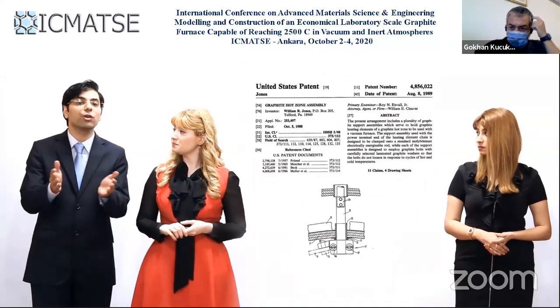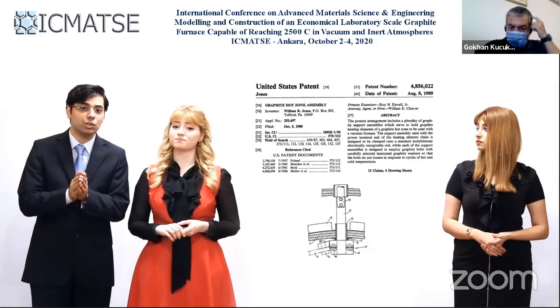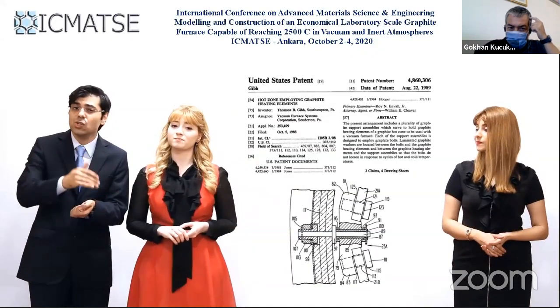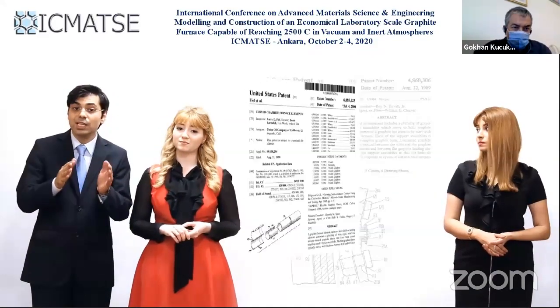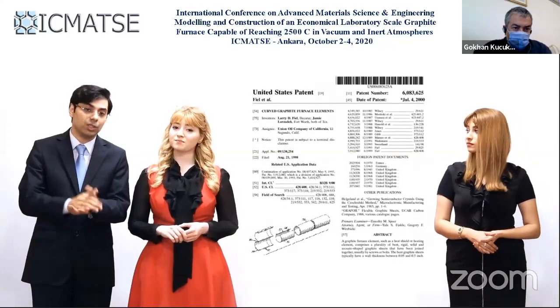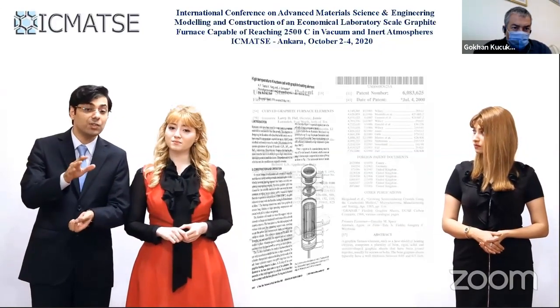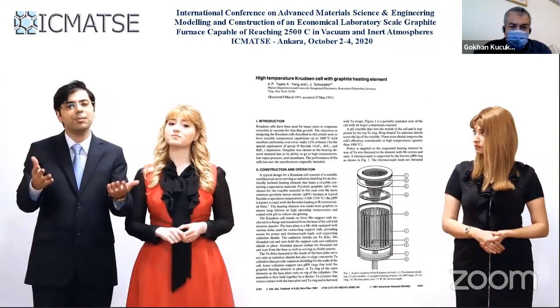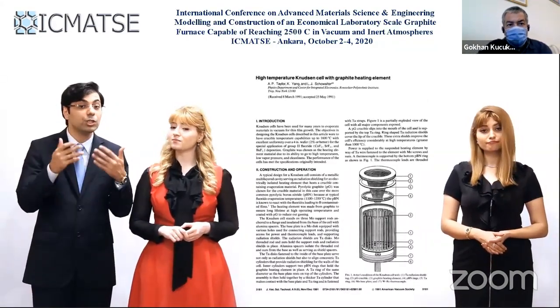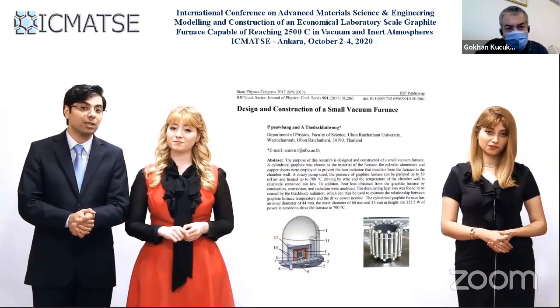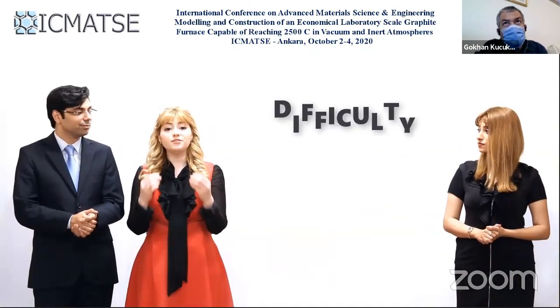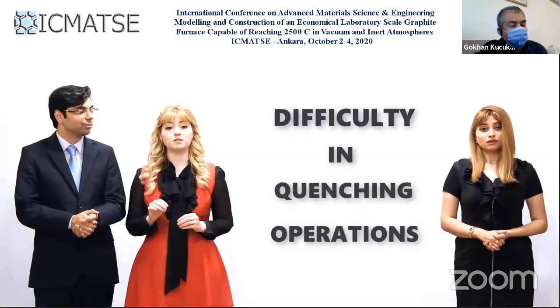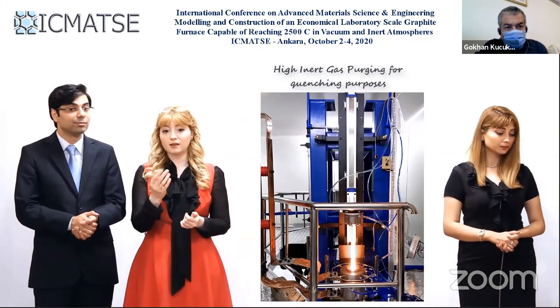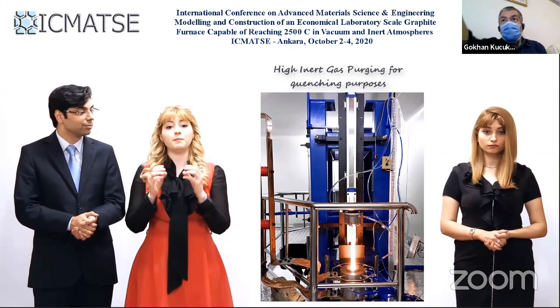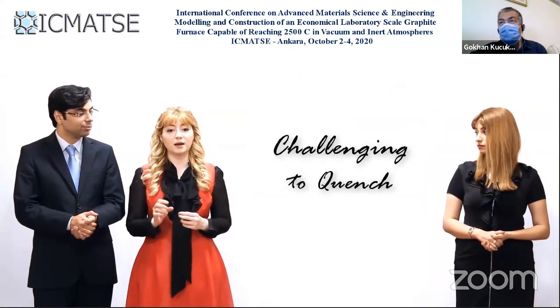It is noteworthy that the majority of available designs require utilization of step-down transformers with ampere ratings of over 1,000 amps, thus increasing the primary cost of the furnace as well as the cost associated with replacing and repairing of the hot zone due to the geometrical setup of the graphite heating elements used in the available designs. An additional problem with graphite furnaces is the difficulty in quenching operations, which tends to be solved through rather operationally inconvenient procedures, such as high inert gas purging as in the case of the silica fiber drawing furnaces, making it rather challenging to quench a sample in vacuum.